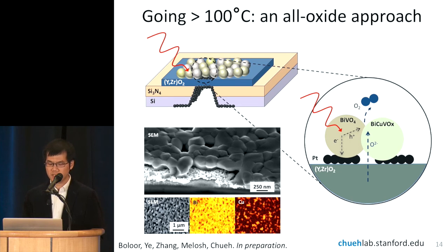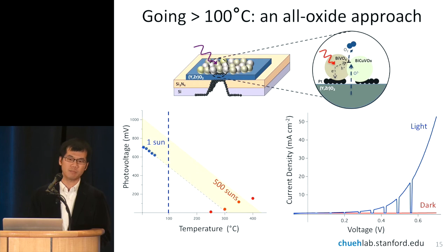So we examine this system as a function of temperature, just like the bismuth vanadate in water. So here is a plot on the left of the photovoltage as a function of temperature. The blue shows you the liquid system, so you can see there's a slight slope. The photovoltage decreases. So we extrapolated that all the way down to about 400 C, and this is where the photovoltage would go to zero. And this is just from the expectation that the material is becoming more intrinsic, so you're losing your junction at the interface. The red curve shows the cell.